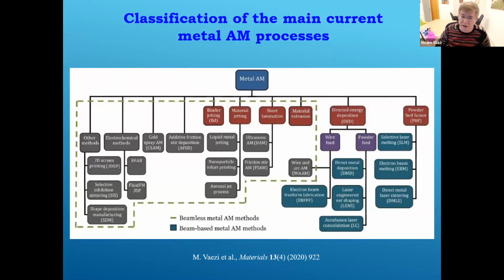The high thermal stress and rapid solidification can lead to detrimental residual stress and defects such as delamination and severe part distortion. In addition, the beam-based metal additive manufacturing systems are energy inefficient and suffer from the high cost of technology and operations, as well as constraints on speed, precision, and surface quality. And moreover, as you will see later, it is quite challenging to process non-weldable metals through beam-based metal AM systems.